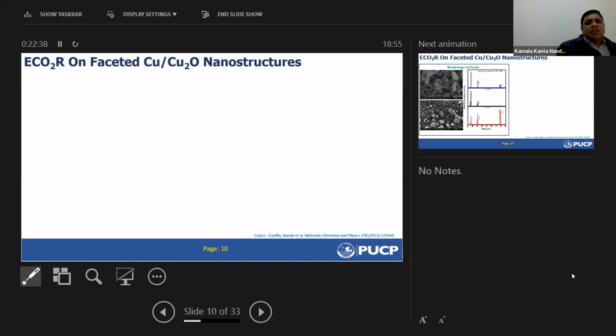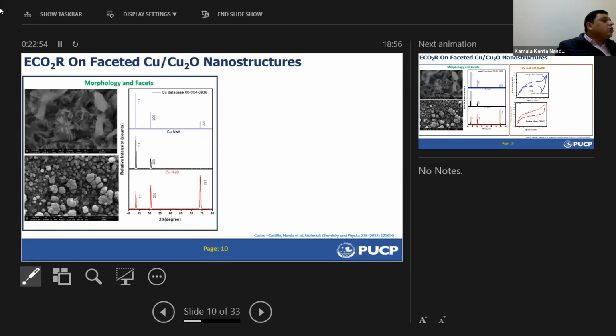Copper is generally oxidized in the atmosphere, so there is a very thin layer of copper oxide. It is not intentional, but it is a natural process. We took copper foil and did electrochemical cycling so that we developed two kinds of nanostructure. In copper nanostructure A, we developed horizontally aligned nanowires, and in copper nanostructure B, we grew nanowires perpendicular to the surface of the copper. Therefore, we expose two different kinds of facets, as can be concluded from XRD. For copper nanostructure B, we have predominantly 100 and 110 facets.